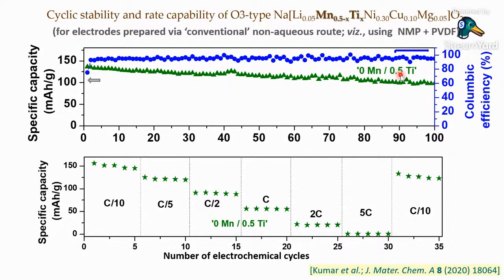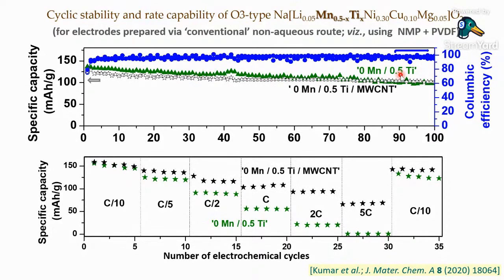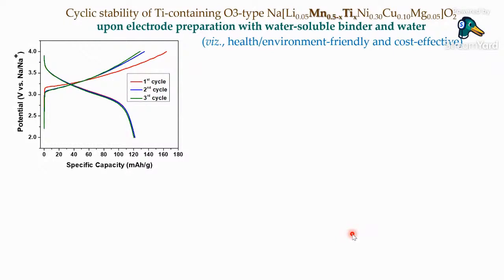Now, to increase the rate capability, we mixed it with carbon nanotube, and that could drastically improve the rate capability as well. So this material can be used for stable sodium ion cell performance, and also draw quite a high current if one mixes it with a little bit of carbon nanotube.